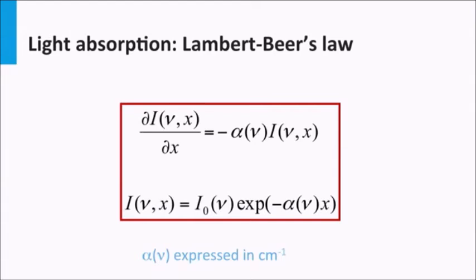The total light intensity absorbed in the material is equal to the light intensity entering the absorber layer minus the intensity transmitted through the absorber layer. For a solar cell, we would like the absorption to be 100%. In this condition, the absorber would be called optically thick. This means the transmission is 0%. From Lambert-Beer's law, it can easily be seen that this can be accomplished by either large values for the thickness d, so very thick films, or large values for the absorption coefficient.